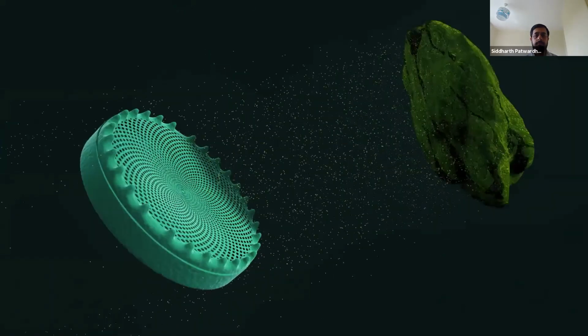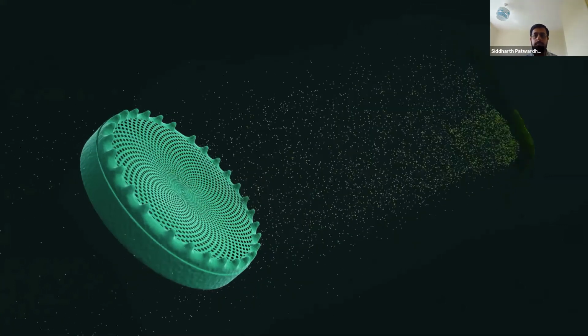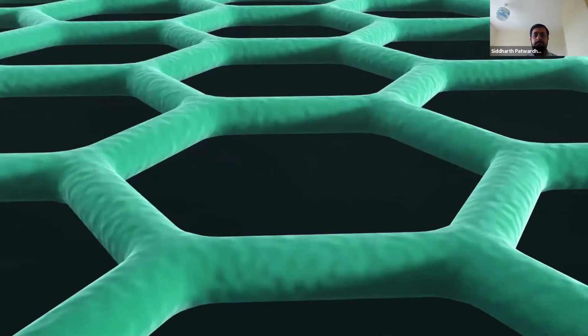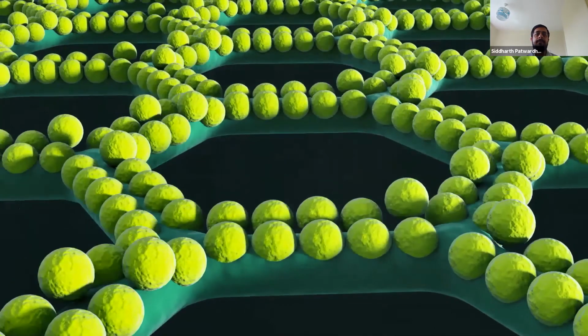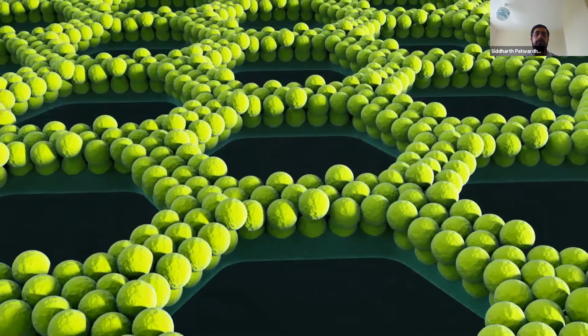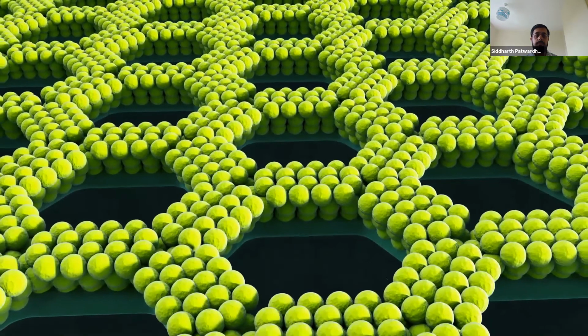It then uptakes that and concentrates it within the cell, and those concentrated pools of the precursor are taken to the site of silica deposition. Now, at the site of the silica deposition, there are proteins and other organic molecules which pre-assemble into the final form, and as the precursor arrives there, it catalyzes the formation and also templates the formation of biological silica, thereby making a cell wall, which is what the diatoms use for their protection.